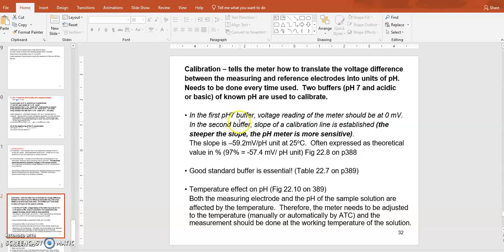You're going to calibrate that pH 7 as 0 millivolt, and then you use a different pH, maybe pH 10 or pH 4 from there, which will give you another set point in millivolt. By connecting those 2 points, you will see the conversion of millivoltage to 1 pH value. If your pH meter is in good condition, the slope of the 2-point calibration should be higher than about 97%, which is about minus 57.4 millivolt per every pH change.